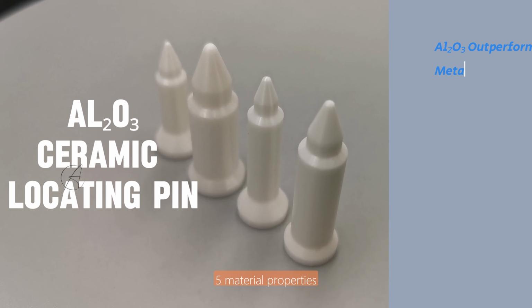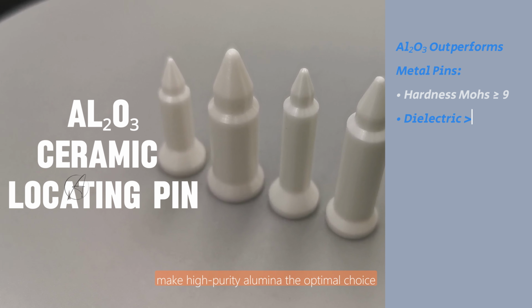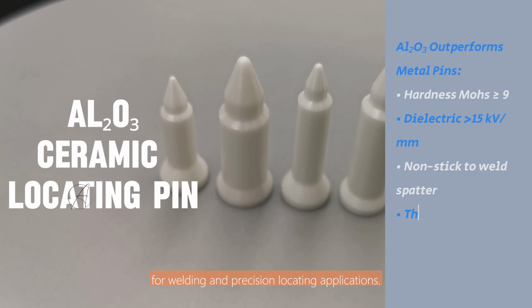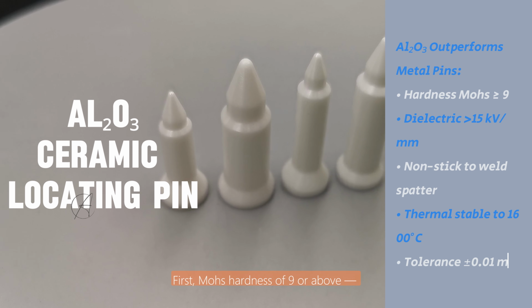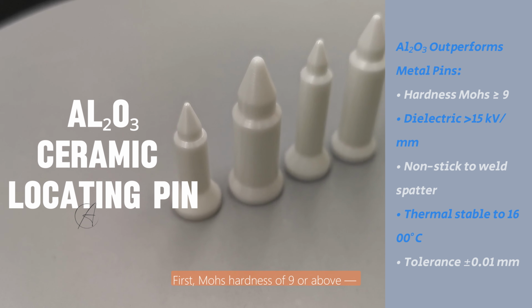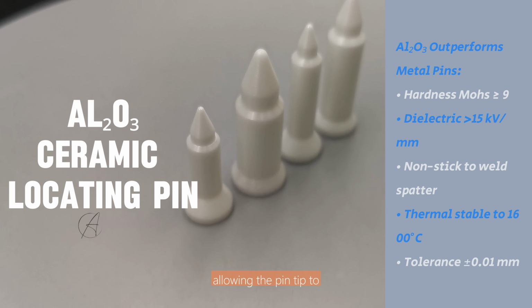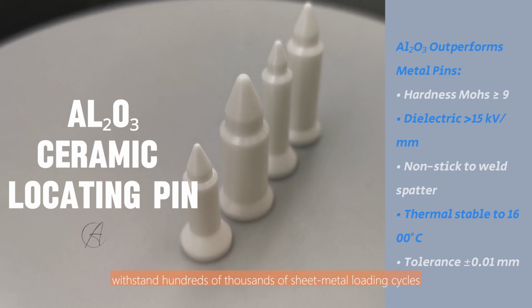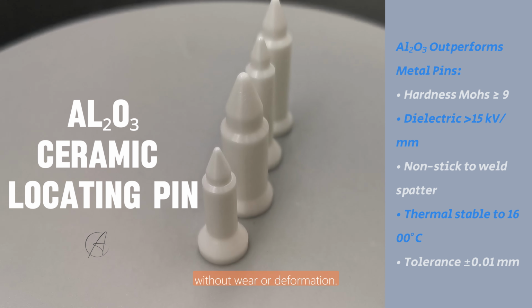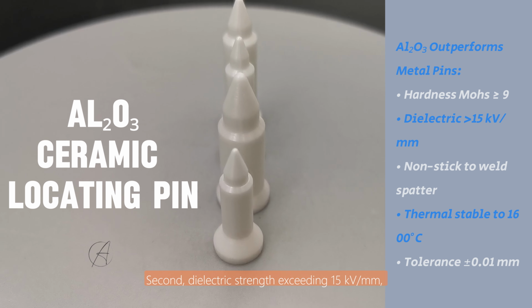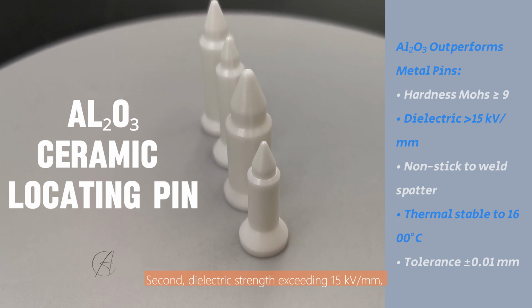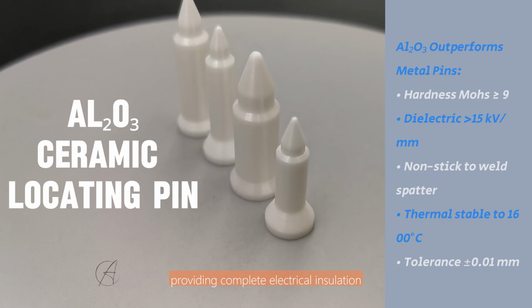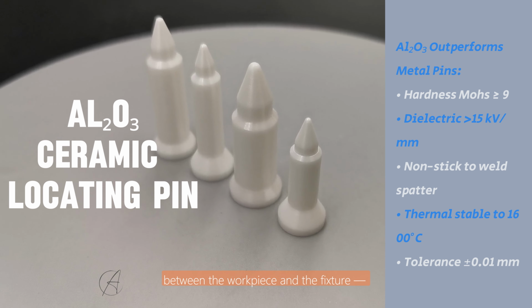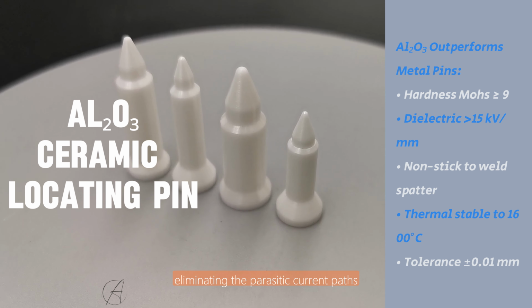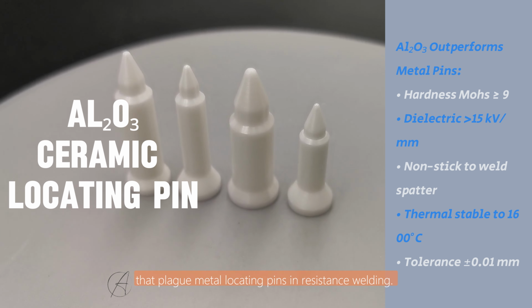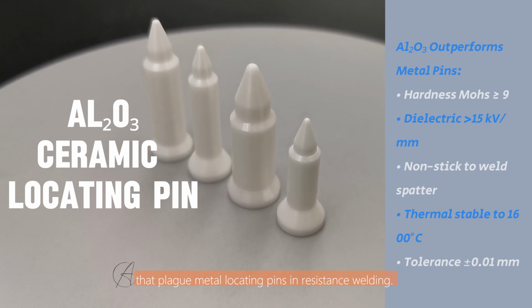5 material properties make high-purity alumina the optimal choice for welding and precision locating applications. First, Mohs hardness of 9 or above, second only to diamond, allowing the pin tip to withstand hundreds of thousands of sheet metal loading cycles without wear or deformation. Second, dielectric strength exceeding 15 kilovolts per millimeter, providing complete electrical insulation between the workpiece and the fixture, eliminating the parasitic current paths that plague metal locating pins in resistance welding.